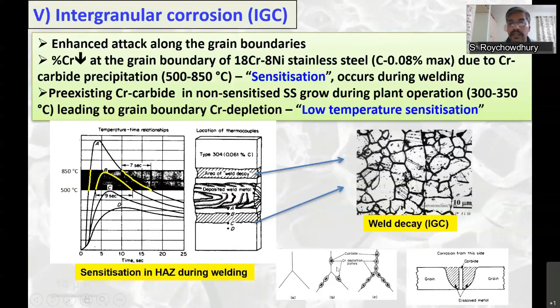So what happens? Chromium carbide forms at the grain boundaries, and Cr23C6 is the formula. So one atom of carbon takes away almost 4 atoms of chromium. So you have a chromium depleted region here. Here the chromium concentration falls below that 11%. So this region adjacent to the grain boundary is no longer stainless, but within the grain, it is still stainless steel. So when it is exposed to the environment, grain boundaries are the regions where it will corrode preferentially. These dark regions are the regions of preferential attack along the grain boundaries.